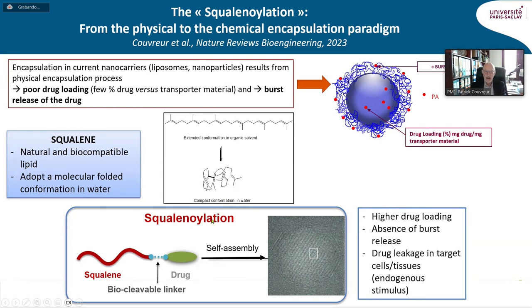And we have taken advantage of this compact conformation of the squalene in water to link several drugs to the squalene, used as a transporter molecule. And very amazingly, after putting this squalene-drug bioconjugate into water, by supramolecular chemistry, the molecules will be able to self-assemble as nanoparticles with a size of around 100 nanometers and with a much higher drug loading than after using